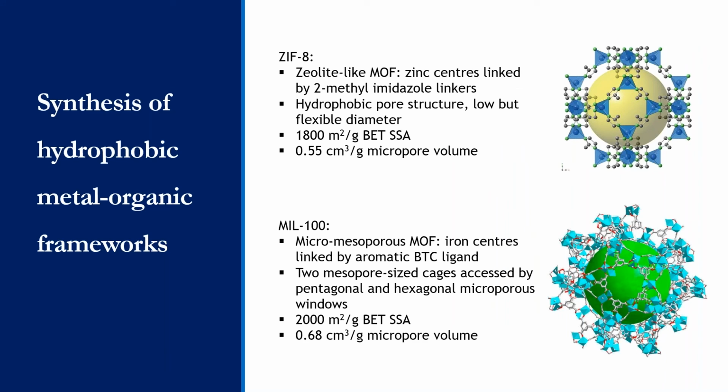And for this, we designed 2 monolithic metal organic frameworks. So metal organic frameworks, or MOFs, are porous materials synthesized using a metal center and some sort of organic ligand, which goes on to attach to the metal center. And this continuous reaction leads to a 3-dimensional porous structure. So we synthesized ZIF-8, which is a zeolite-like MOF with small apertures and very hydrophobic chemistry, and also MIL-100, which is a micro-mesoporous MOF. Both materials have a high degree of micropore volume, above 0.5 centimeters cubed per gram, and surface areas in the range of 2,000 meters squared per gram.